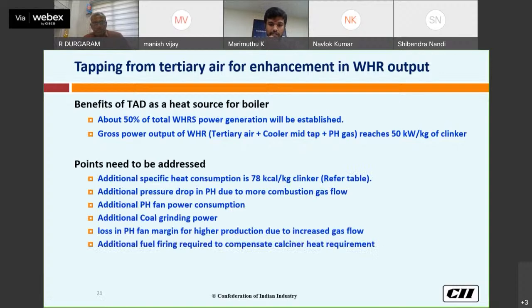The points to be addressed: because part of the heat which we give to the calciner is taken for the WHR, the specific heat consumption will increase. So this is the case for 5000 TPD. And the additional pressure drop in the PH due to more combustion gas flow we have to take care of, so additional PH fan power consumption also. If you want to add more heat to the calciner, definitely coal will be required, so coal grinding power we need to consider, and the loss in PH margin for high production due to increased gas flow also has to be taken into account.